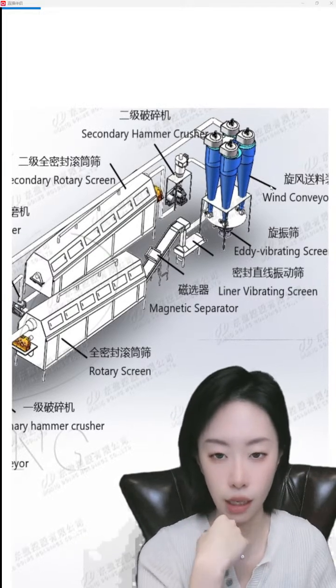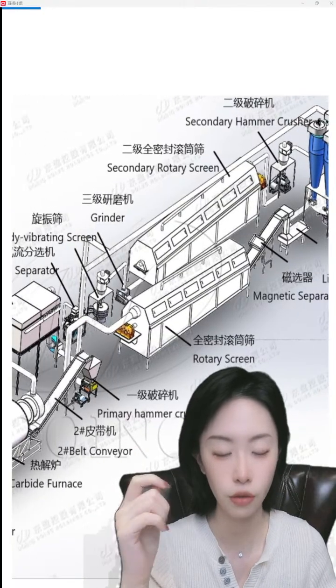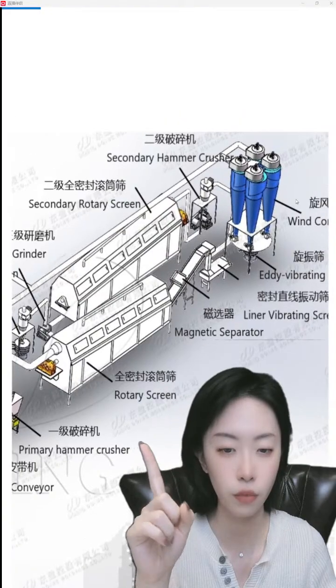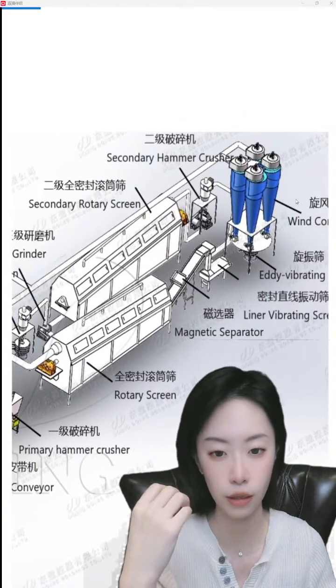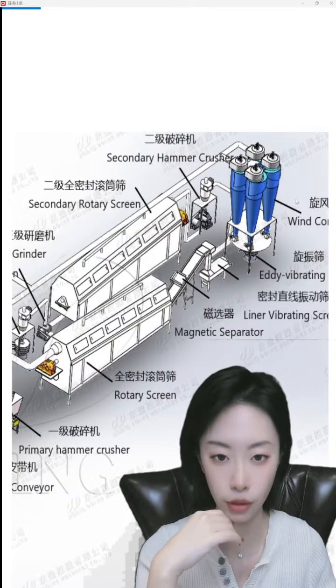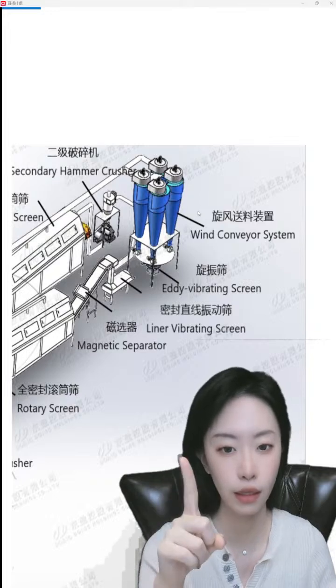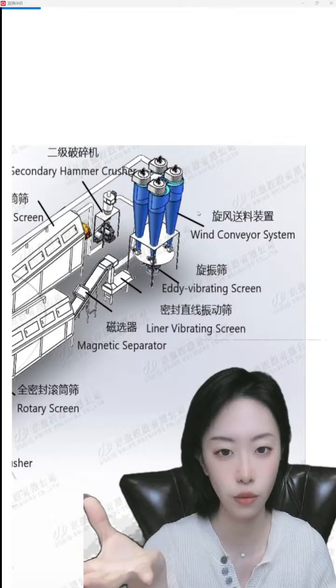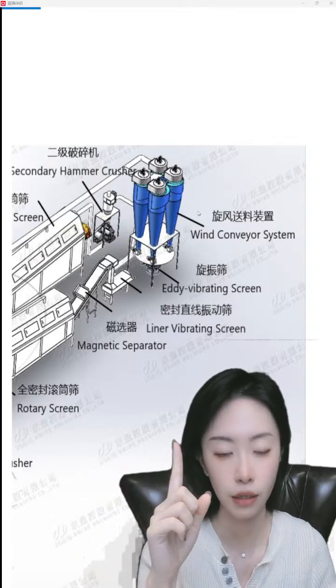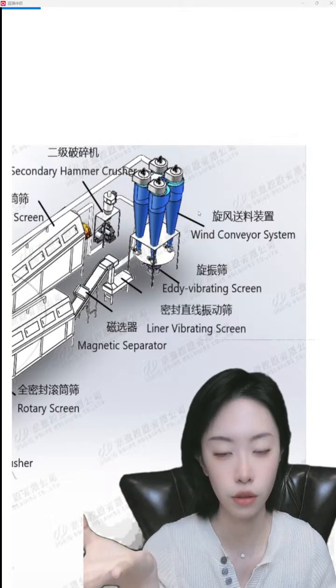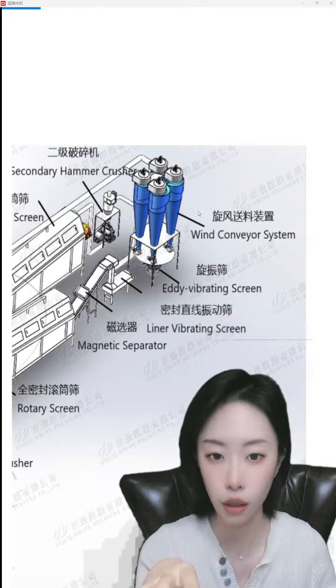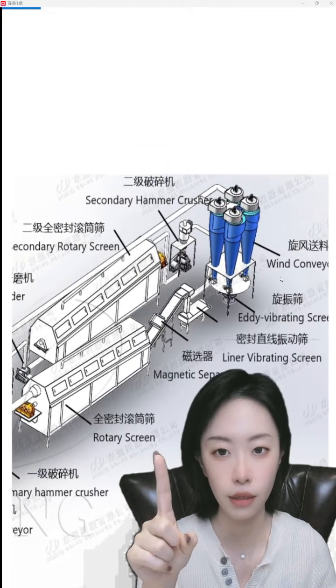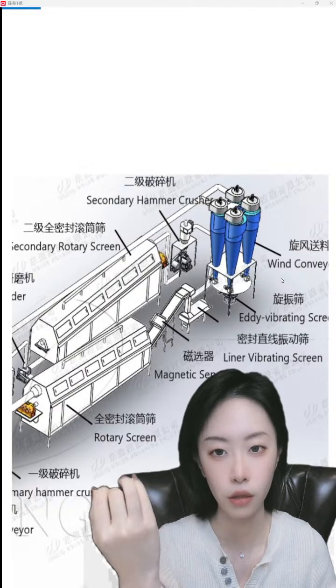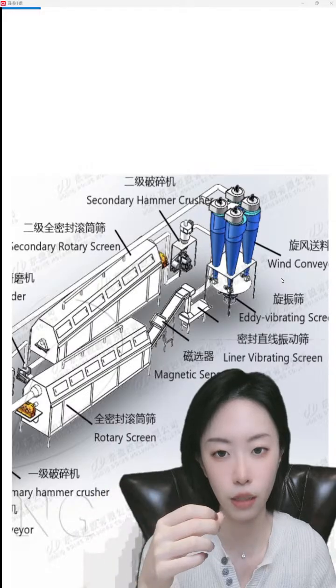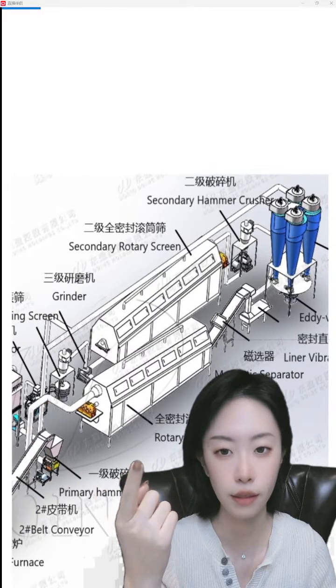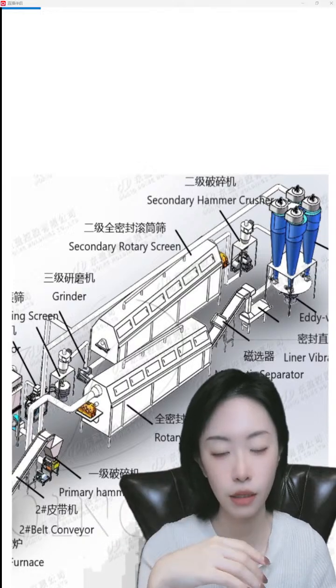And here is the whole processing line. First crusher crushes particles into 10 mm, and then the rotary screen separates nearly 70 to 80% of the black powder. The magnetic separator separates the iron, the linear vibrating screen separates the diaphragm, and then the second hammer crusher uses the crushing blade to crush the particles into 6 millimeters. Then the second rotary screen gets 10% of the carbon black.